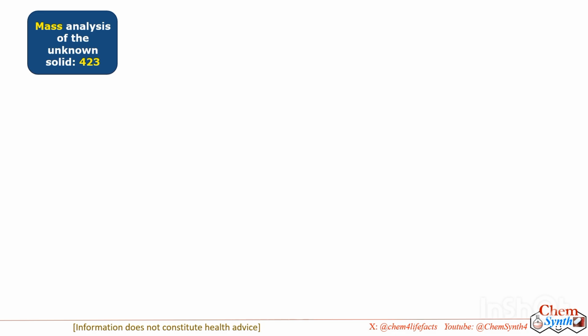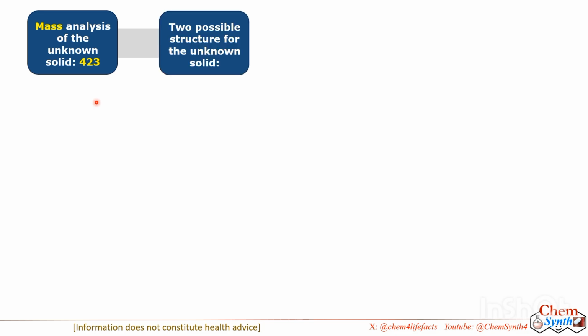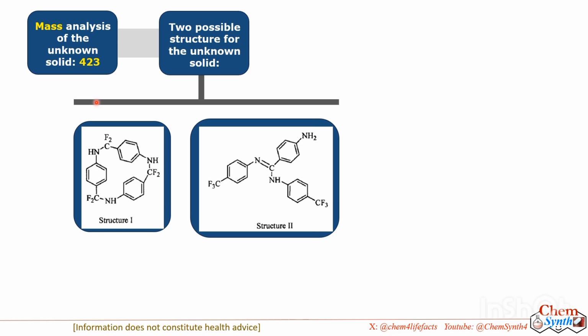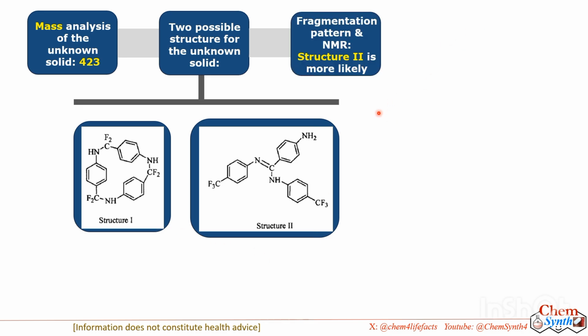A further analysis they attempted was mass spectroscopic analysis for the solid material, and the observed mass was 423, where the mass of the para-CF3 aniline molecule I mentioned in the first slide is 161. So this observed mass is around 3 times. Based on this mass observation, they proposed two possible structures for that unwanted solid material, structure 1 and structure 2. These molecules are kind of trimers of the original molecule. One is cyclic, another is acyclic. From the fragmentation pattern of the mass and from the NMR spectroscopy, they concluded that structure 2 is the most likely structure for the unwanted solid material.